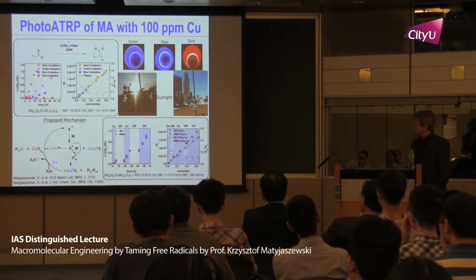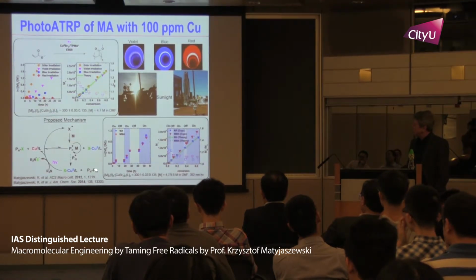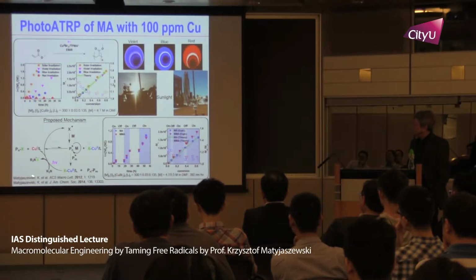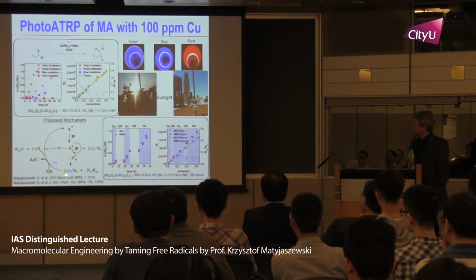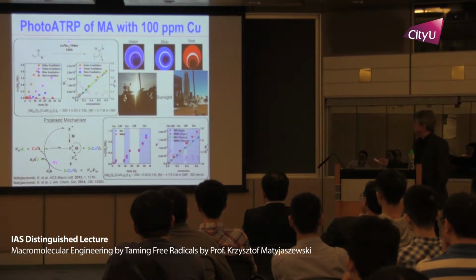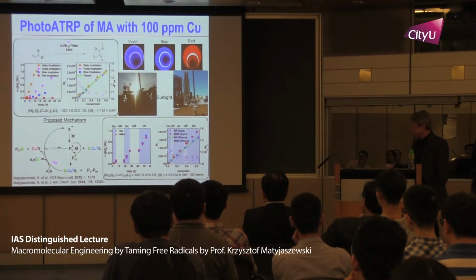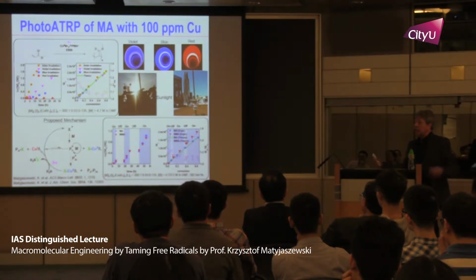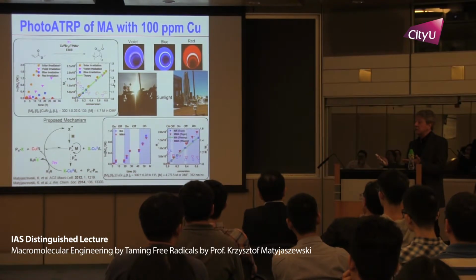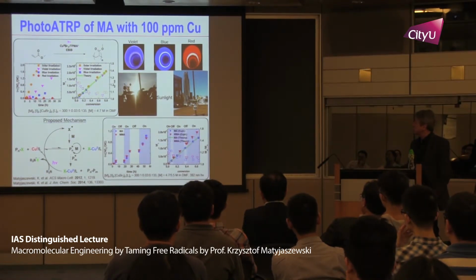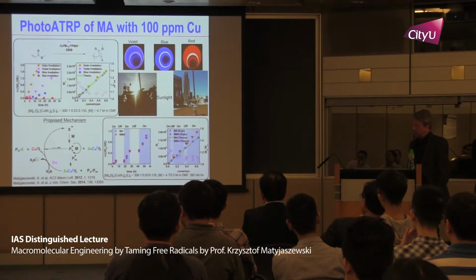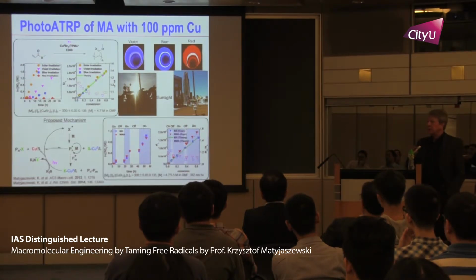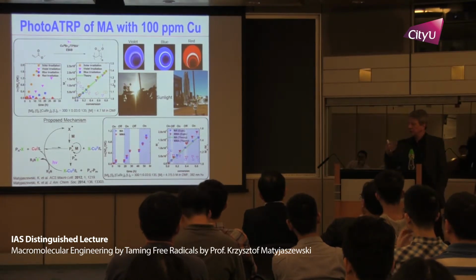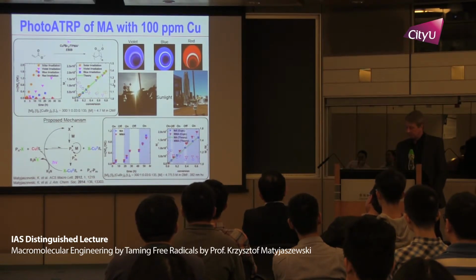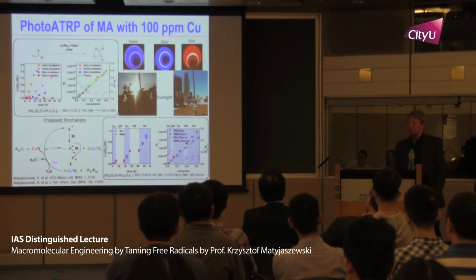So really what happens under these conditions, you excite copper 2 species in the presence of electron donor, it is reduced to copper 1 and activates the process. Because we are using a very small amount of copper, once you stop irradiating, radicals terminate, copper 1 gets oxidized to copper 2, and the reaction stops. So it will be on-off, on-off, on-off reaction. Sometimes for electronic materials, something which Professor Alex Jen is interested in, maybe we can remove total copper.